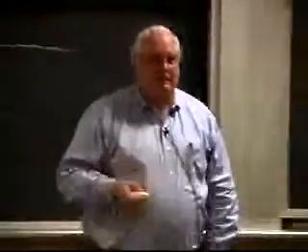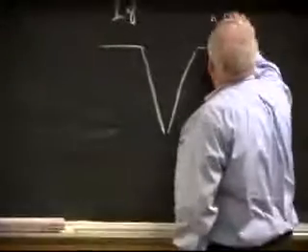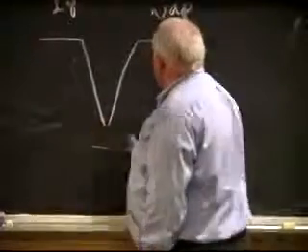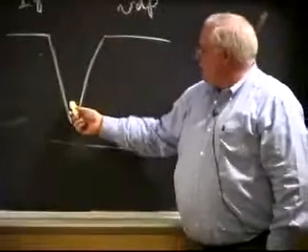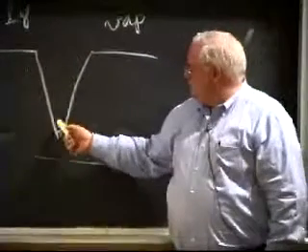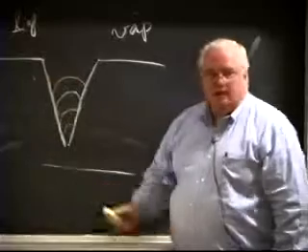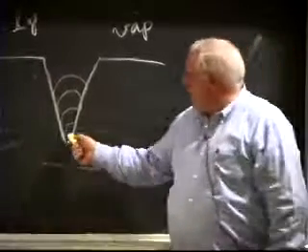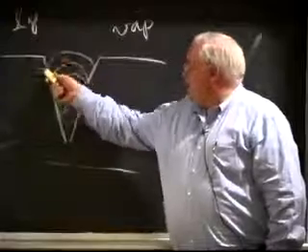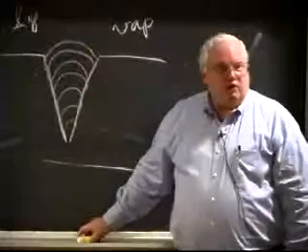If you think of trying to put a liquid on top of a solid, you can't solve this problem. However, if I think of putting a vapor on this and having a temperature gradient, so that I've got a hot steam up here and this thing's being cooled, I will vapor deposit the water in here down from the bottom, and as it condenses down in here, its wetting angle is still non-wetting, but now it's non-wetting in the proper direction.